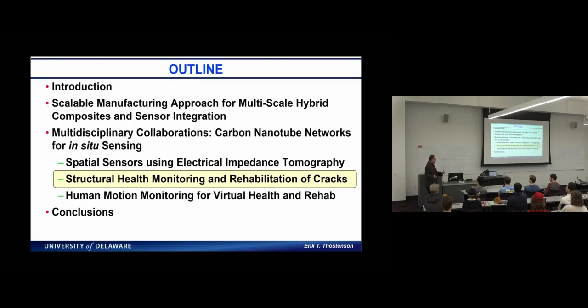And of course, deterioration of infrastructure is even more of an issue today. And the DelDOT engineers were like, yeah, this is great. They saw some very nice results where they didn't have to replace the structure, but they could rehabilitate it, bring it back up to its original load condition. They said, all this is great, but you covered up the damage. We can't go and inspect it. So our idea was that, well, we could use these sensors that we developed in the lab to monitor the growth of damage underneath a composite repair.